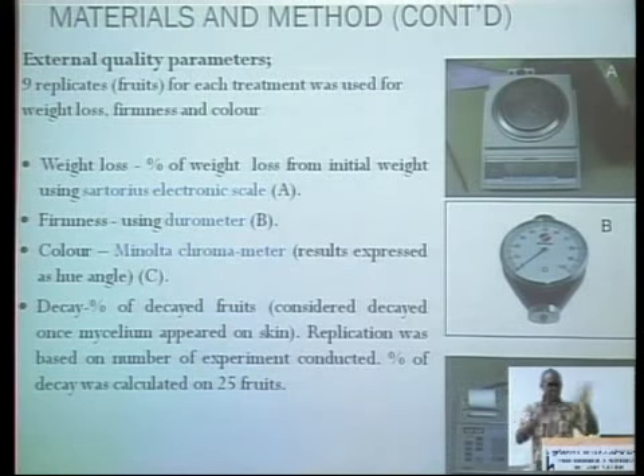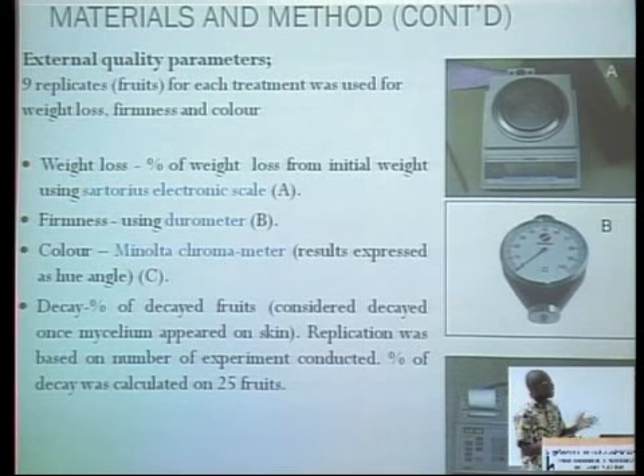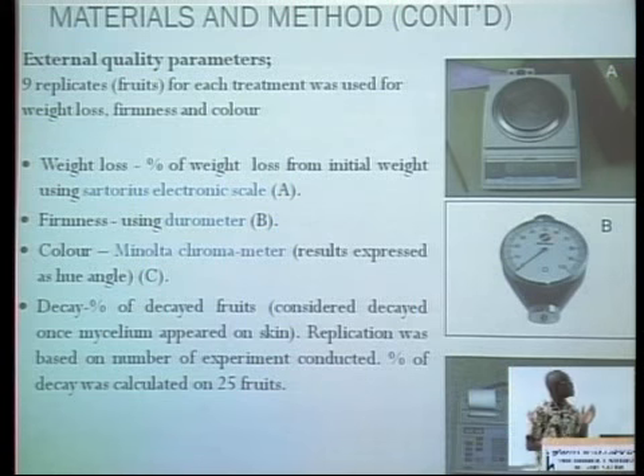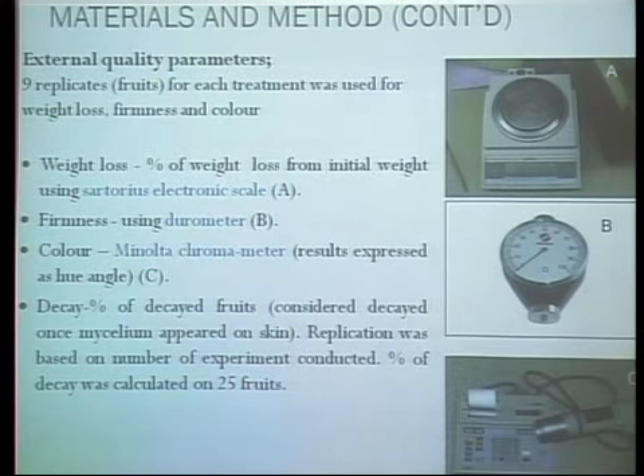Now, after the heat treatment, like I said earlier, we have to take all the parameters. The parameters had to be taken in such a way that we had to destroy the fruit at a point in time. So we had the destructive and then the non-destructive. The non-destructive basically has to do with the external qualities. So we look at the weight loss, the firmness, the color, and then the decay. For weight loss, firmness, and color, we used 9 fruits representing the 9 replications. And for the decay, we took into consideration all the 25 fruits.